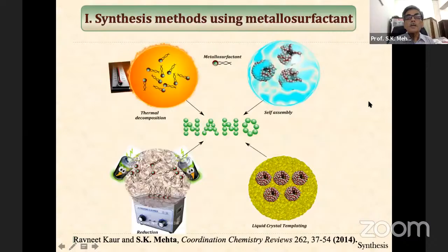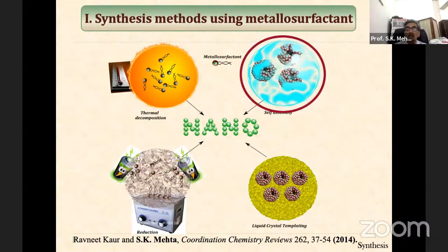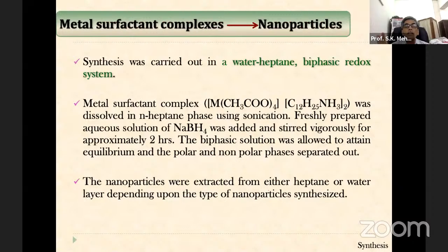Okay. So the idea was very simple. We can have this metallosurfactant. We can create self-assembly of these metallosurfactants, or otherwise you can use the method of thermal decomposition, or even the method of reduction. You can also do liquid crystal templating. All these procedures can be done. So we preferred the self-assembly, where you create the self-assembly of these metallosurfactants, and then you can convert them into nanoparticles. So the idea was very simple.